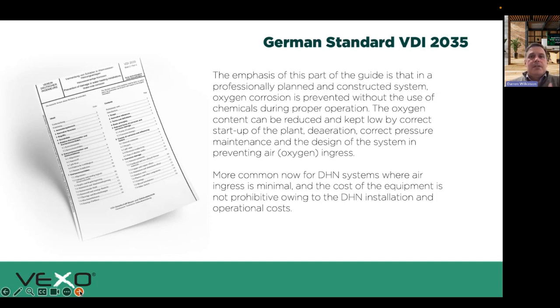And what makes water more corrosive? Obviously oxygen does, but also the conductivity of the water can make water more corrosive. Imagine demineralized water, very low conductivity. As we start adding our chemicals, we'll see the conductivity start to increase. However, we've got inhibitors in there that mitigate any risk of corrosion because of the conductivity. But with the VDI standard, they take the oxygen out. You remove the mineral content, not all of it. We don't want it completely removed, because otherwise we'll end up with leaching of brass fittings, etc. So it's normally 50 to 100 microsiemens.